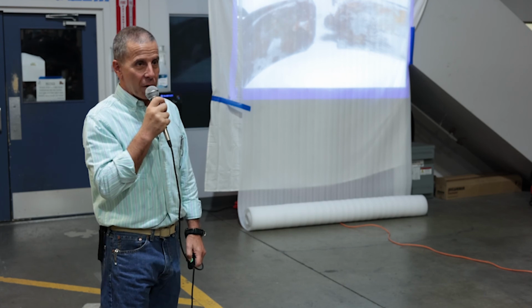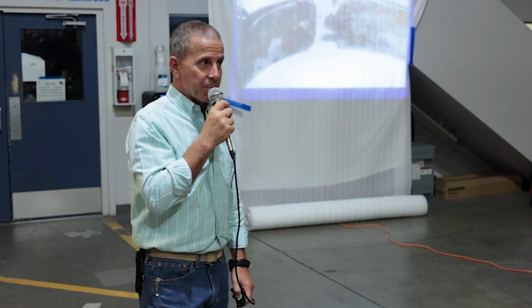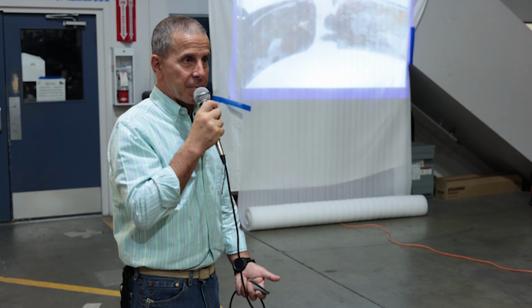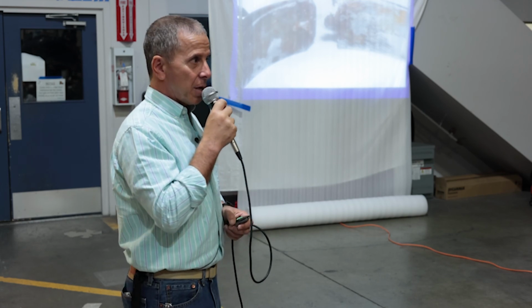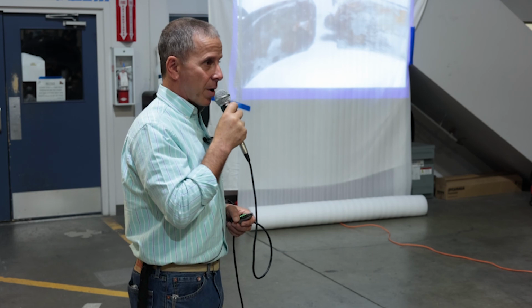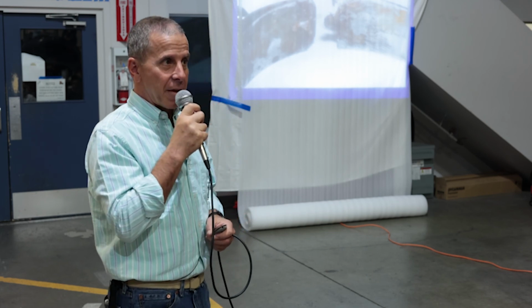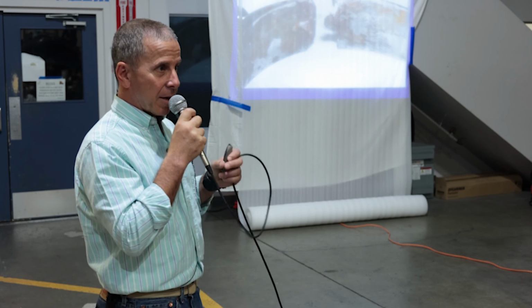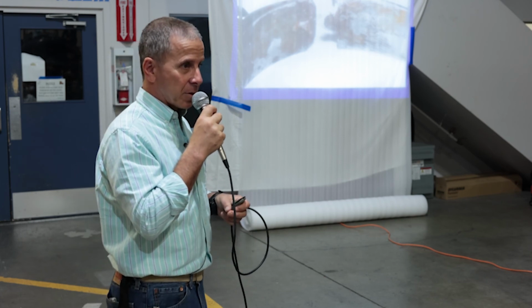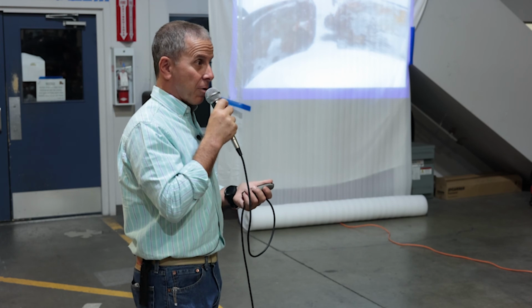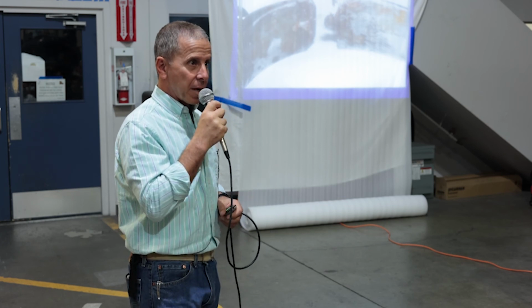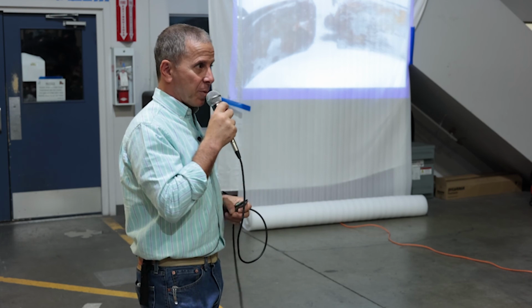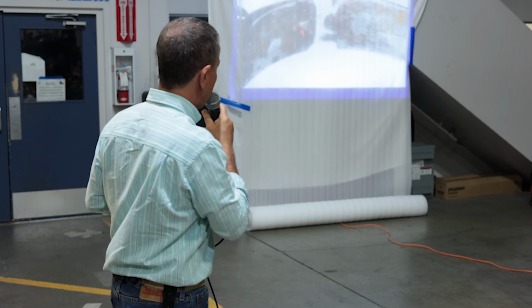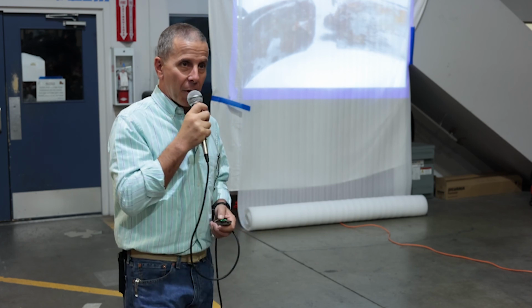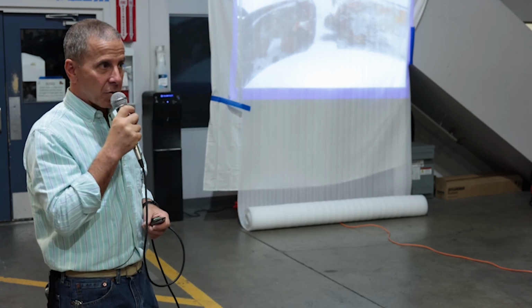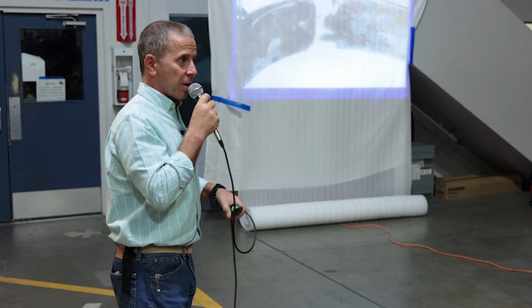Hose clamps are notorious for this type of failure, especially what I call a T-bolt clamp, the type of clamp that you would use a socket wrench to tighten. It has a nut on it rather than just a screw head. Those are made up using a flap of stainless steel that traps water. Again, notorious for this, especially if it's in an area like near a bilge or even in a bilge. Water getting into that flap between the two pieces of stainless on the clamp, like the one that's shown here, sets up a perfect environment for crevice corrosion.